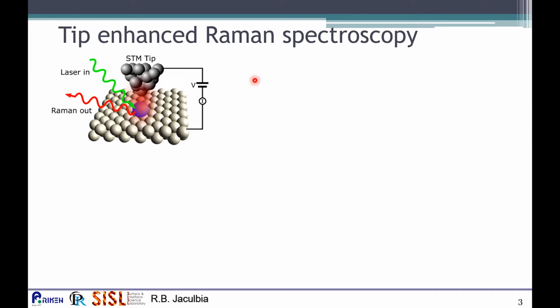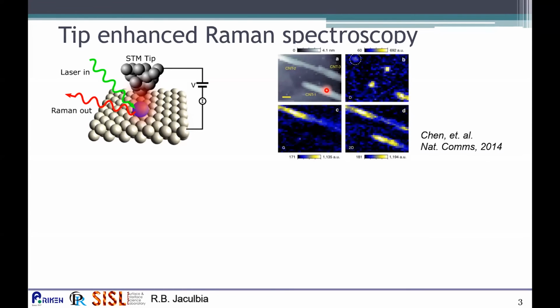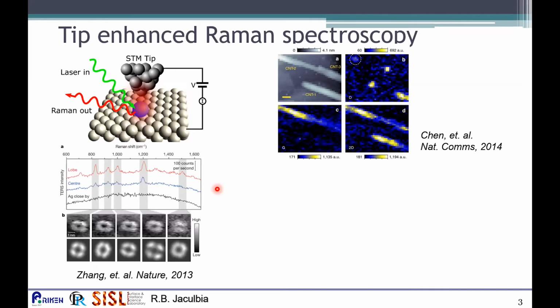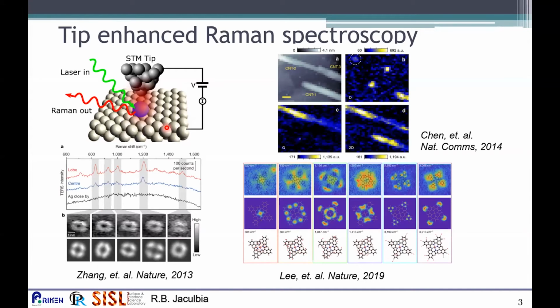And in fact, tip-enhanced Raman spectroscopy, specifically STM-based TERS, has been applied successfully to different kinds of materials, such as carbon nanotubes, wherein in ambient conditions, spatial resolution as high as 1 nanometer was obtained. And also, it was successfully applied on single molecules in ultra-high vacuum and low temperature conditions, first reported in 2013. And more recently, it was shown that STM-based tip-enhanced Raman spectroscopy can be used to identify individual vibrational modes.